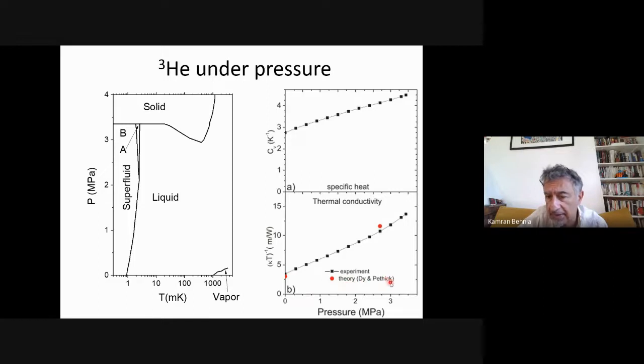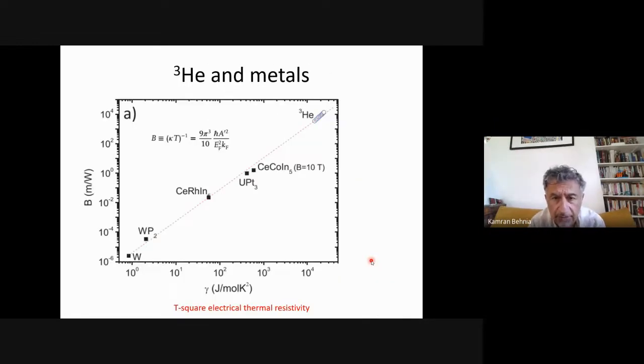This is a theory by Dy and Pethick, the Fermi liquid theory, just by taking the Landau parameters and calculating the thermal conductivity. So theory works. Now, let's come back. And this is what was not done before 2020 for reasons that I don't understand. If you put now helium-3 and compare it with this term in metals, basically I am using the same data. You see the number in the case of helium-3, and for the other metals, this is basically the slope of WT, which I call B. They match.